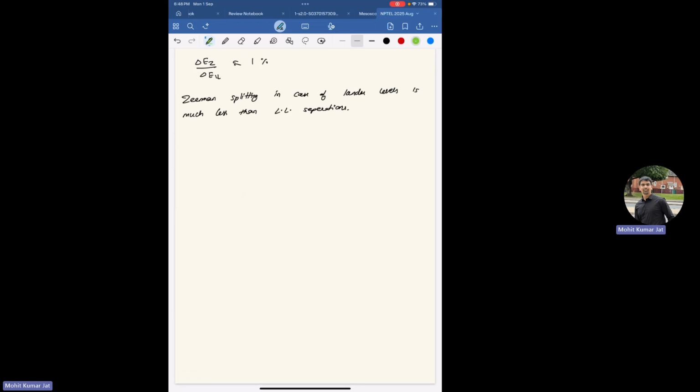Because you have to change your filling factor, ν = nh/eB, you'll have to change it by either varying n or B. And in case of graphene, since it's a semi metal, a Dirac metal also, you can tune the Fermi level by tuning the gate voltages, and that's what I will be discussing.